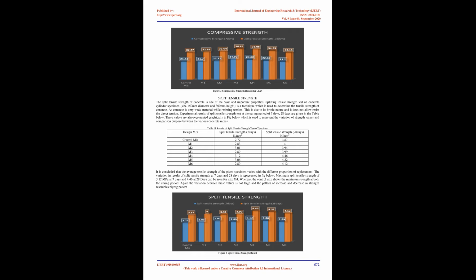With the addition of waste and recycled material, an improvement is seen in compressive strength. In the beginning, the strength increases as the percent of replacement of bagasse ash, marble waste powder and RCA increases till mix M3, as M3 attains the compressive strength of 36.45 MPa. But after mix M4, the compressive strength tends to decrease till mix M6. Minimum strength was found to be 32.15 MPa for mix M6 at 28 days. All the mixes show little variation with respect to each other. But the variation in M3 with respect to the reference mix is high, as there was an increase of approximately 4 MPa in its strength.